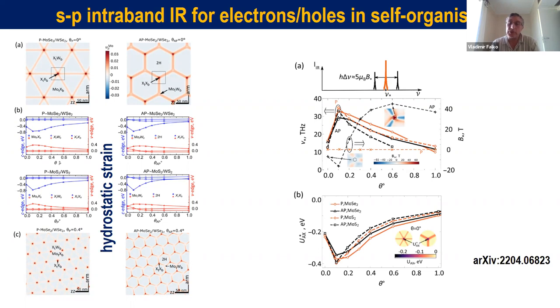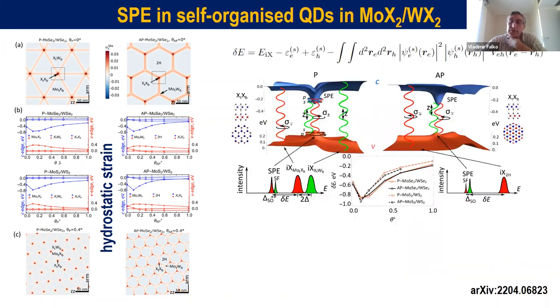For the range between 0 and 1 degree, these quantum wells for electrons and holes appear to be so deep that they host not only the lowest S state, but also the P-type state bound in the same quantum dot. So one can start looking into the physics of intra-dot terahertz transitions in those systems. But most importantly for us, we now have the electrons and holes localized in the same place.